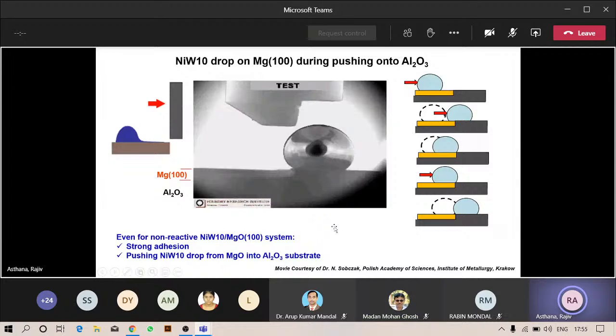So again, we are looking at some systems where you can have high adhesion, even though wetting is not very good. So in this case, if you see, the liquid is actually pulling up this substrate because the bonding is very good, even though the contact angle that we measured was not very low. So it's a non-wetting system, but high adhesion.